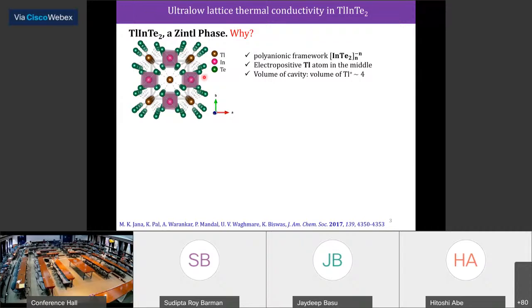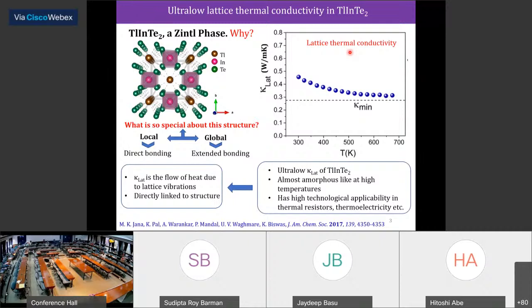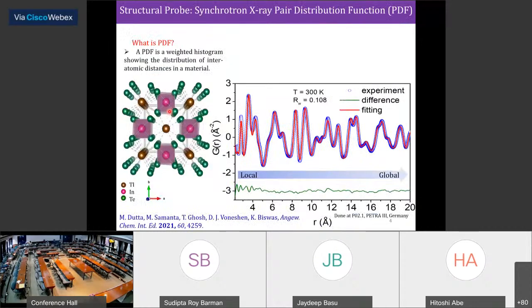In 2017, we showed this compound has ultra low thermal conductivity, very very low compared to many state of the art materials in the field of thermoelectrics, and we tried to understand why. One of the reasons could be bonding hierarchy, because it has covalent bonding and ionic bonding. So this is very interesting: two different substructures, one having weak bonding, another having strong bonding. That was the motivation for starting that work, and we tried to understand more by pair distribution function analysis at the PDF beamline at PETRA.